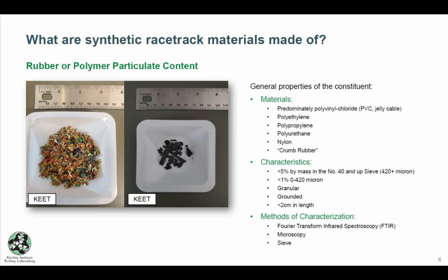The rubber particulate, here is a good example of what made the poly tracks, or at least the older tracks, black. A lot of it was because they had this crumb rubber in there, and it has a material called carbon black, and that stuff leaches out, and that's kind of what turned the tracks black over time. But we still see that it's common to add in what we call the jelly cable. It's like when you strip an electrical wire, it'll be that type of material that makes it in. And again, this is something that we can test for and identify what's present in the material.